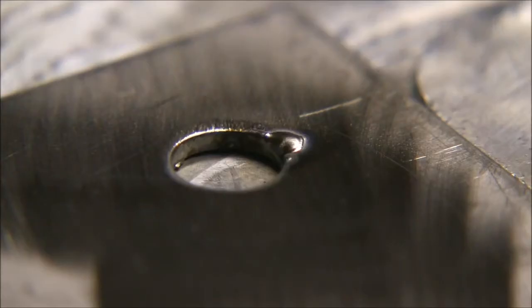Now, same size electrode, just much smoother wheel used, a smoother sanding belt used to sharpen it, and it's pretty good. It still wanders just a little bit at start at really low amperage, but once I get it up to 10 or 15 amps, it's pretty stable. Not a problem there. It wasn't ideal on the startup. A smaller electrode would have worked better and given me a nice crisper start, but this is actually acceptable for something like this. So 3/32 electrode for filling in a hole on 18 gauge would work.